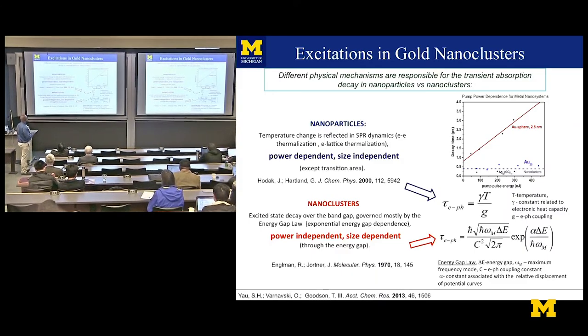Well, so this is kind of a summary of what this means. We had evidence now that big particles behave like we expect them. They are governed by the surface plasmon, which is a temperature dependent thing, but these clusters now seem to be of a different nature. They're independent of this kind of coupling constant of the electron phonon system and governed by the energy gap law.